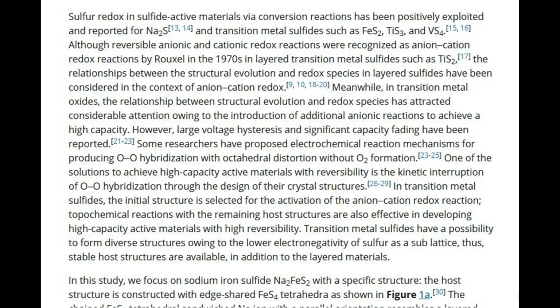Meanwhile, in transition metal oxides, the relationship between structural evolution and redox species has attracted considerable attention owing to the introduction of additional anionic reactions to achieve a high capacity. However, large voltage hysteresis and significant capacity fading have been reported.21-23 Some researchers have proposed electrochemical reaction mechanisms for producing O-O hybridization with octahedral distortion without O2 formation.23-25 One of the solutions to achieve high-capacity active materials with reversibility is the kinetic interruption of O-O hybridization through the design of their crystal structures.